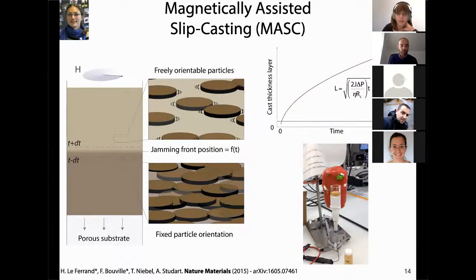The suspension is basically our particles inside water, or any solvent actually. You tune the composition of the slurry so that the particles are freely movable. They can move around, they can be oriented, and you obtain a very liquid slurry. And you pour it on a porous substrate, so it's a gypsum substrate in general, or plaster. A very cheap one, but very easy to shape.